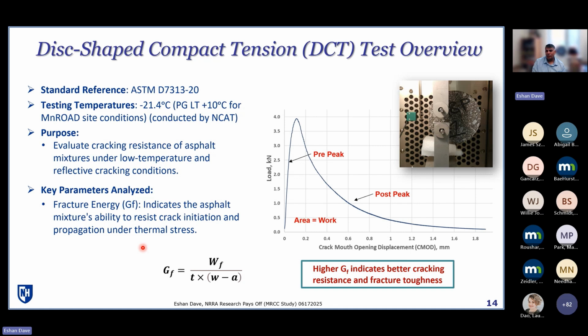The second part that we also need to know is what happens to these mixes just under the thermal action of cooling. Because if you recall, all of these pavements, whether they have a joint underneath or not, as winter comes and temperatures drop, are going to try to strain because of thermal shrinkage, and that will do two things. One, it will generate a tremendous amount of thermal stress, or tensile stress, in the asphalt mixture, but it will also make these mixtures a lot less ductile, or less tolerant to strains,